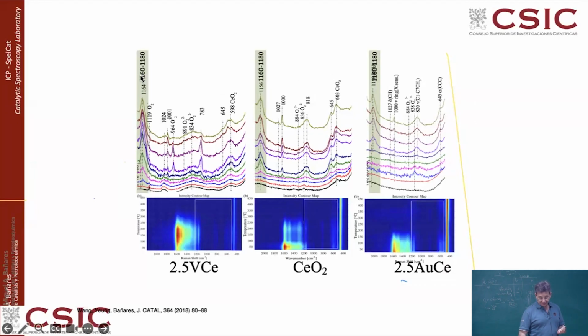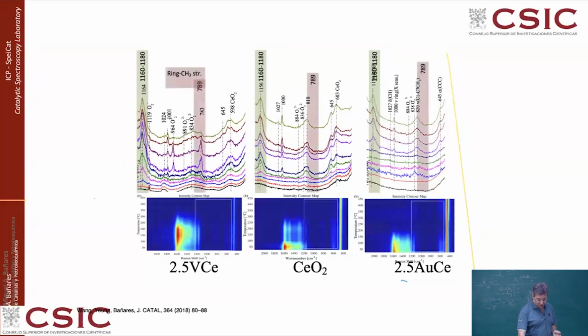The three catalysts present this band at 1160, which is typical of adsorption of toluene in any configuration. So basically this band is not giving you much information about how toluene is adsorbed, but it is telling you that yes, you have toluene adsorbed in any form. Now, toluene may adsorb in different manners. In the case of vanadium on ceria, you get this additional band here at about 790 that you do not observe on ceria or gold ceria, which is basically associated with the stretching vibration of the aromatic ring with the CH3 group of the toluene molecule.